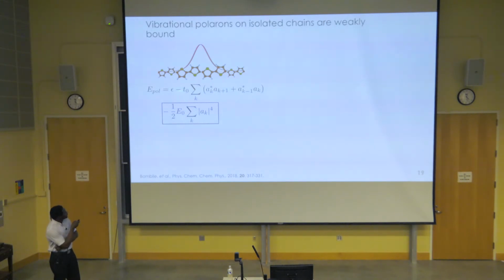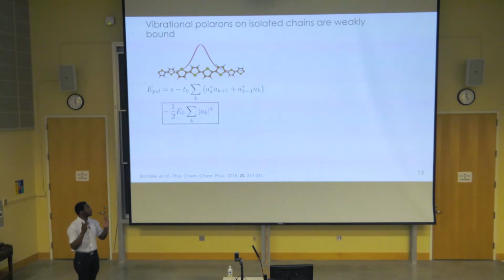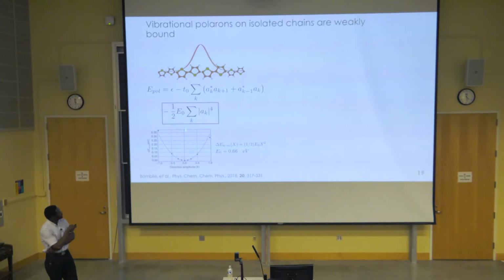And I should mention that this first term, like the hopping term, tends to delocalize the charge carrier, and the second term here, the stabilizing term, wants it to be confined in a small region of space. Upon optimization, I should mention that we determine the characteristic constant for the reorganization of nuclei using first principles simulation based on density functional theory, and we are able to determine this constant.